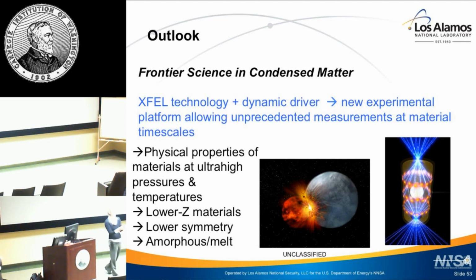We've tested down to as small as, say, 1 or 2 micron probe, and there we see almost immediate X-ray damage. But does this mean the temperature is higher than the Hugoniot? Well, on purpose we don't select such a tiny spot size. We can record tens or hundreds of events in a row at the, say, 50 to 80 micron spot size, and we see no change in the diffraction. So then when we actually do pass the shock through the sample material, we know that there's no contribution from the X-ray with those parameters.